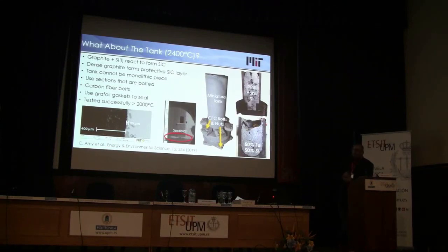It's difficult to say because we can't look at it when it's hot. We see it when it cools, but it's possible that those particles formed on the cooling event. So here you can see some silicon carbide, and there's silicon carbide in the silicon as well. Small particles, but it's difficult to know whether or not they were there when it was hot, or if they were just dissolved in the liquid, or if they formed upon freezing. Or maybe detached during liquid metal movement. Possibly, yeah. Then you produce something like slurry. Right, and we've